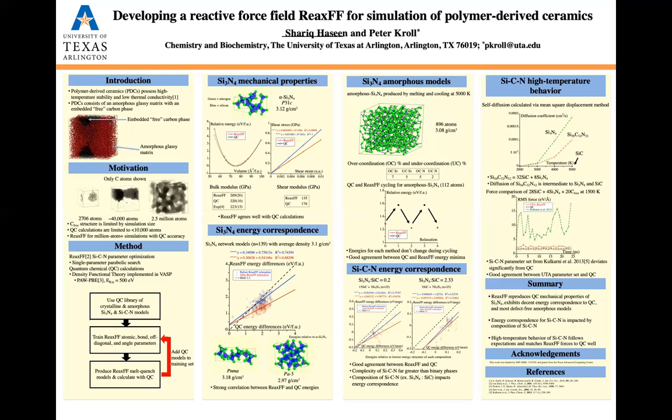Thus, we parameterize a classical reactive force field, ReaxFF, for performing million-atom simulations with accuracy comparable to quantum chemical calculations. So we train ReaxFF parameters to investigate silicon carbonitride polymer-derived ceramics. Our focus is on training silicon-nitrogen and silicon-carbon-nitrogen parameters. Using our extensive library of silicon nitride and silicon carbonitride structures, we train parameters to reproduce quantum chemical energy differences and forces. Resulting parameter sets are refined through a self-learning process.